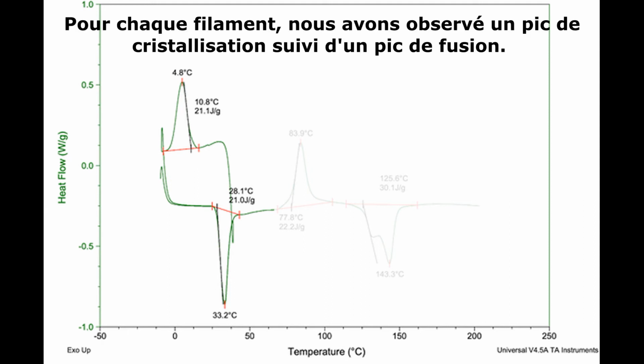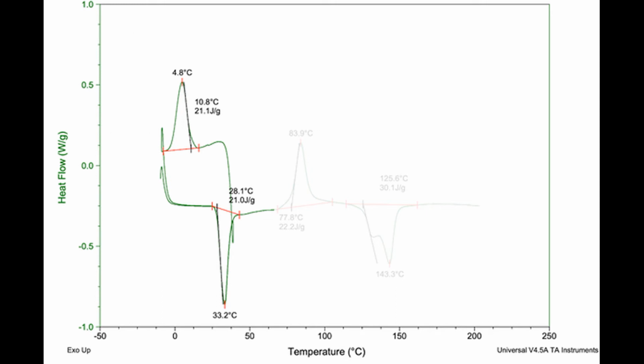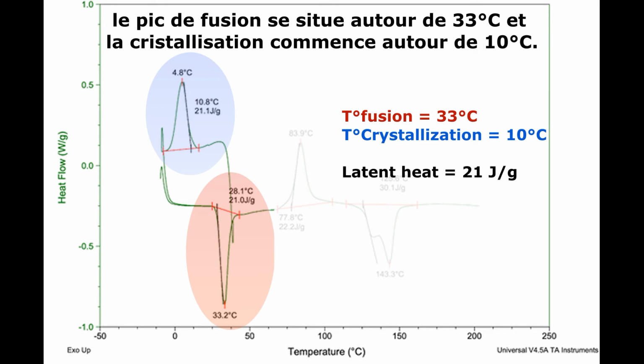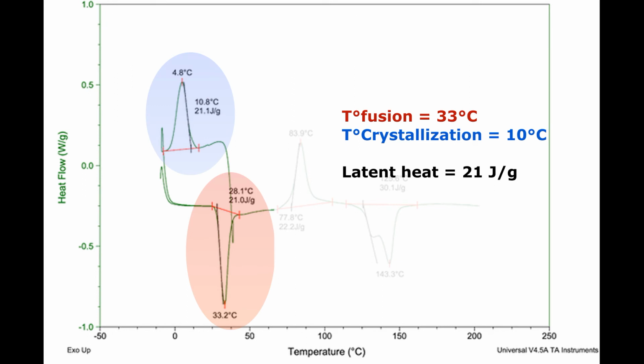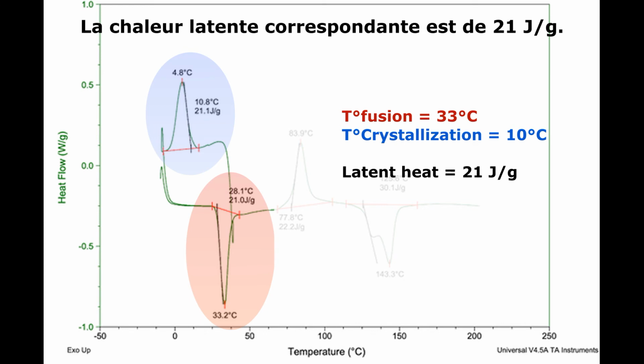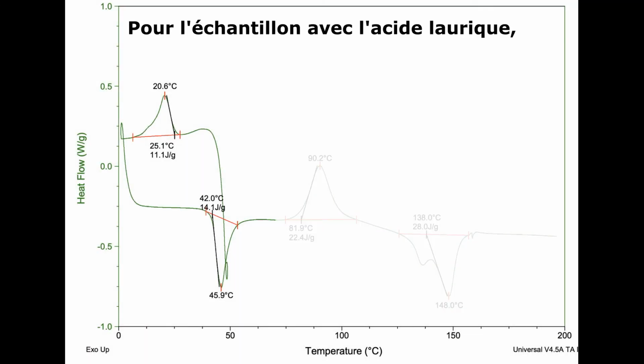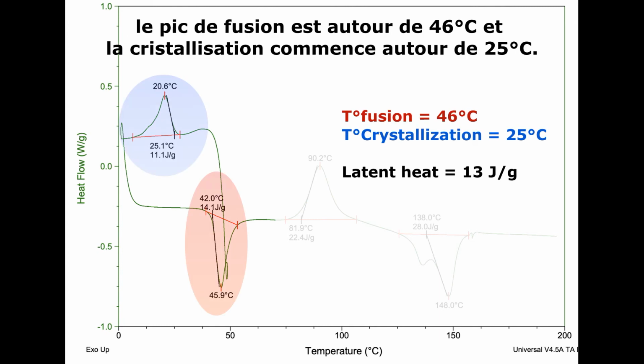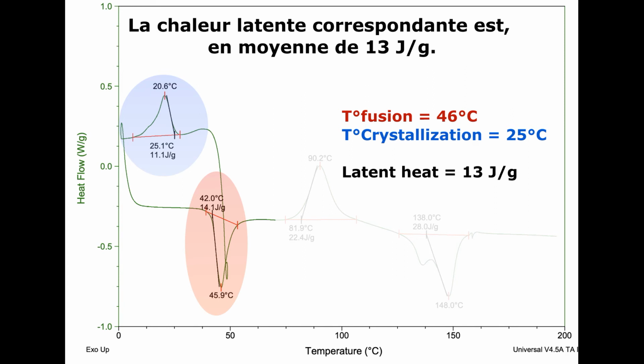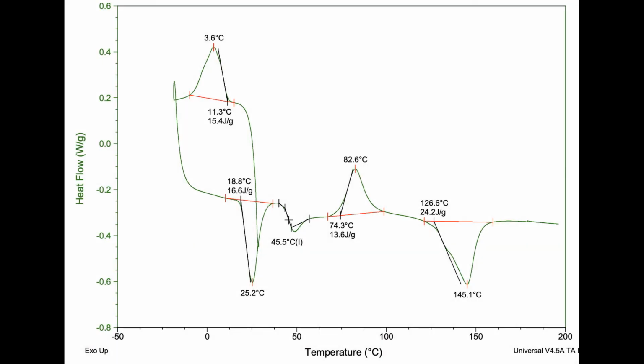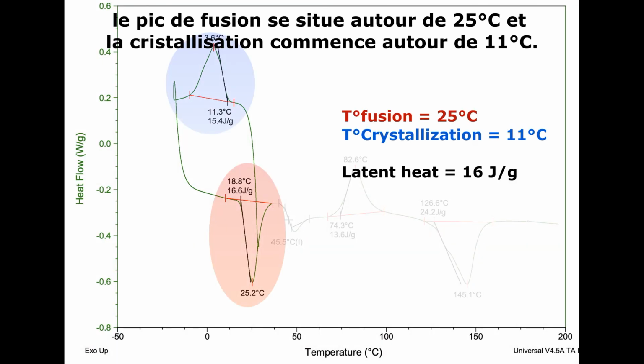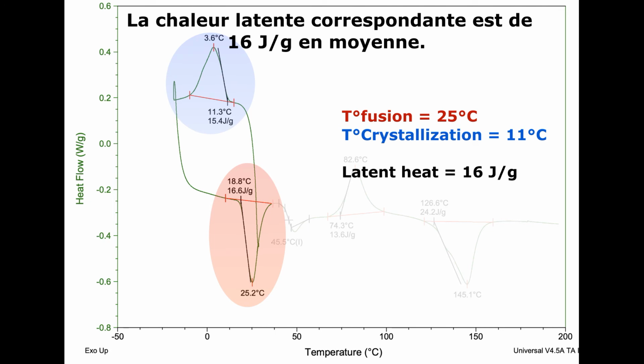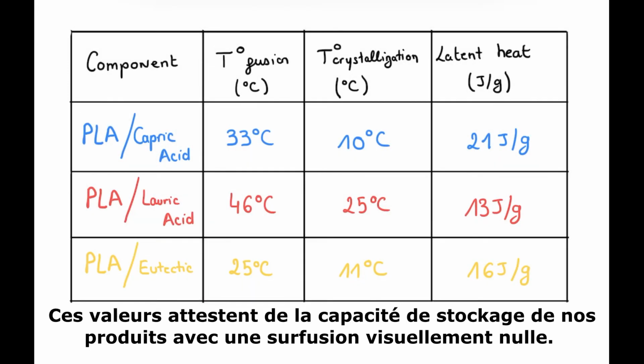For each filament, we observe a crystallization peak followed by a fusion peak. For samples with capric acid, the fusion peak is around 33 degrees and the crystallization starts around 10 degrees. The corresponding latent heat is of 21 joules per gram. For the sample with lauric acid, the fusion peak is around 46 degrees and the crystallization starts around 25 degrees. The corresponding latent heat is, on average, of 13 joules per gram. Finally, for the sample with the eutectic, the fusion peak is around 25 degrees and the crystallization starts around 11 degrees. The corresponding latent heat is of 16 joules per gram. These values attest to the storage capacity of our products with visually no supercooling.